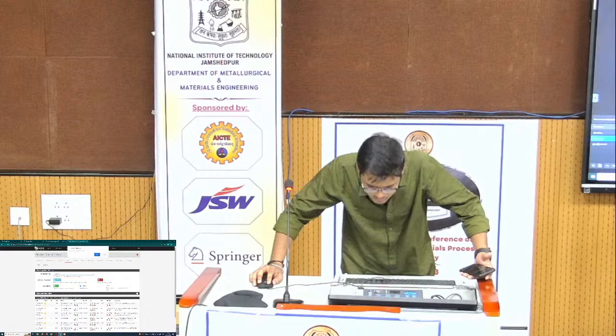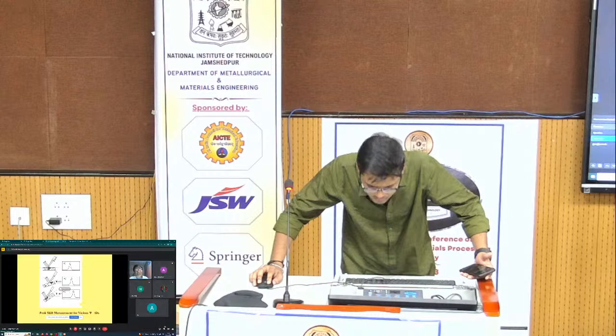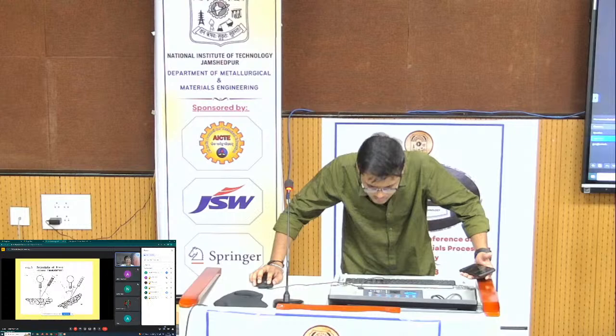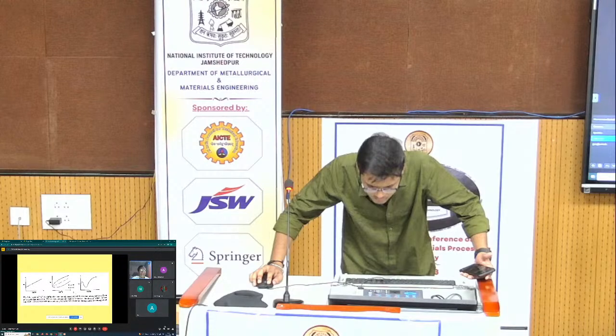So the most important thing is, this is how we start. This is how we say this is a perpendicular orientation. Let's say these are the 2-1-1 planes which are parallel to the surface. Then now your X-ray and the detector remain in the same direction, but the sample has started rotating. That means essentially we are talking about the same 2-1-1 planes but differently oriented, and see how they are shifted. So this shift is most important, and that's how the principle of X-ray is taking place. And this shift is what we measure, delta 2 theta, and that gives us the stress.